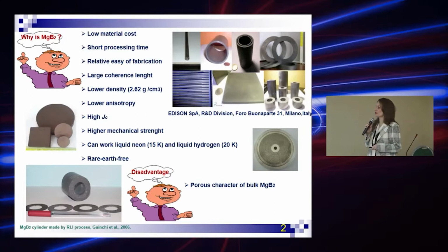Since the discovery of superconductivity in MgB2 materials at 39 Kelvin, enormous efforts have been made on processing, characterization, and applications. Its superconducting transition temperature is lower than the other high TC materials, but its BCS features allow a large coherence length and a high critical current density. I tried to gather the other advantages of this material, so I called this section: why is MgB2 so special?